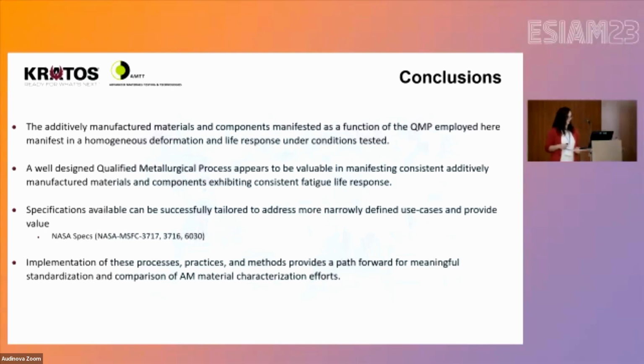And I'll wrap it up here with those conclusions that we were able to manifest homogeneous and isotropic specimens, not only in deformation and life response, but because of those qualities, we were able to get consistent fatigue life response. And the exciting news is specifications available out there already can be successfully tailored to address your potentially more narrowly defined use cases. And the implementation of those processes, practices, and methods provides a path forward for meaningful standardization and comparison of additive manufacturer material characterization efforts to really leverage the work that everyone's doing.